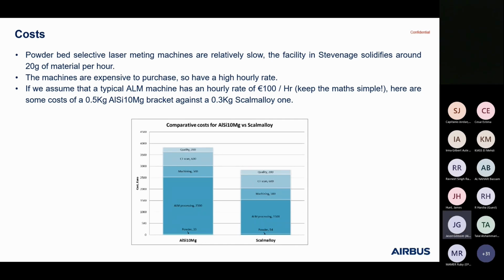Now, if you're going to redesign that part using Scalmalloy, what we've typically seen is you save between 30 and 50% mass. So if we now say the redesigned Scalmalloy part is going to be 0.3 of a kilogram for the same load cases, and we've done quite a few studies comparing the two materials, as I said, between 30 and 50% savings. So if we save around about 40% to go middle value. Now, Scalmalloy typically is around about 200 euros per kilogram, so nearly 4 times the cost, but we're now only using 0.3 of a kilogram of it compared to 0.5. Yes, there will be a bit of wastage as well. But the key thing is that the AM processing time, because we've now only got to deposit 300 grams, is that the time attributed to the machine cost is €1,500.